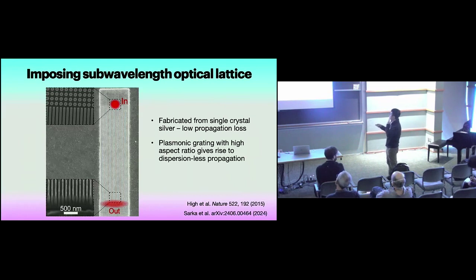So you are looking at some single crystalline silver, and we just etch a bunch of trenches, just a bunch of gratings, into this single crystalline silver. And what I can do is to pump the system from this in-coupling structure, and the surface plasmon polariton gets excited, and they will propagate along these gratings, and will be diffracted from this out-coupling structure. I emphasize single crystalline silver because one of the issues with plasmonic structures is that they typically have high loss. Here you can have low loss because of this